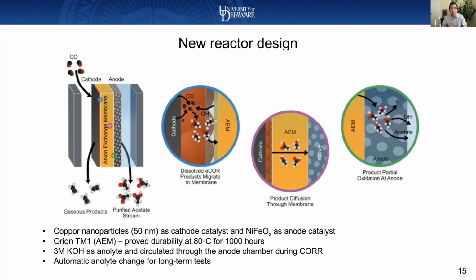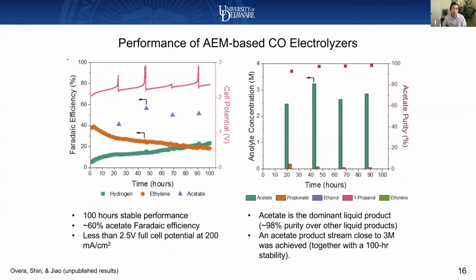And we really are trying to push the stability test to not just a few hours, but hundreds of hours. So here is some of the preliminary results I want to share with you. Interestingly, what we saw is that we can maintain roughly 100 hours of stability for this particular system at a cell voltage of roughly 2.3 volts. And you can see there are some spikes in the potential profile. The reason for these spikes is that at the end of 24 hours, what we did to the system was replace all the electrolyte with a fresh 3 molar KOH electrolyte. That's why the potential suddenly dropped to roughly 2.2 volts, then steadily increased.